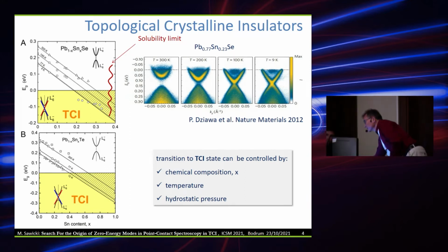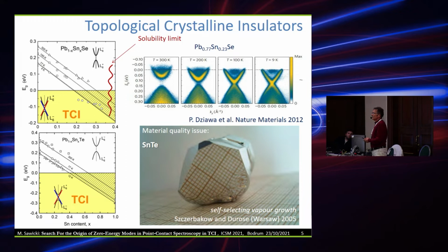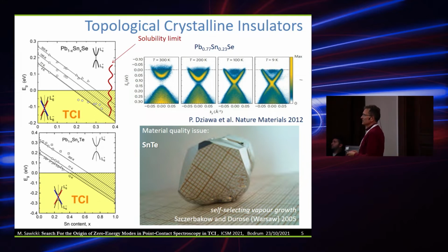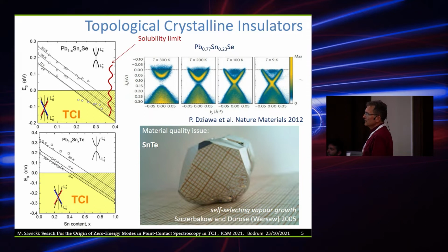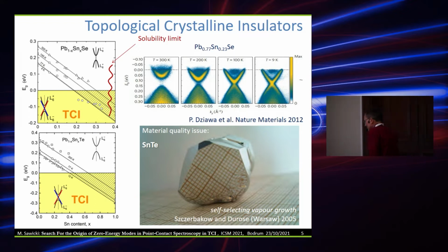of tin. The next very important part of our study is that we are studying bulk crystals, and it has been elaborated more than 15 years ago, a growth method in which we are obtaining macroscopically large crystals of very high quality, and as you can see, they can be easily cleaved into giving us mirror-like surfaces of very high quality, and particularly that kind of cleaving can be done at high vacuum, which enables the ARPES studies.